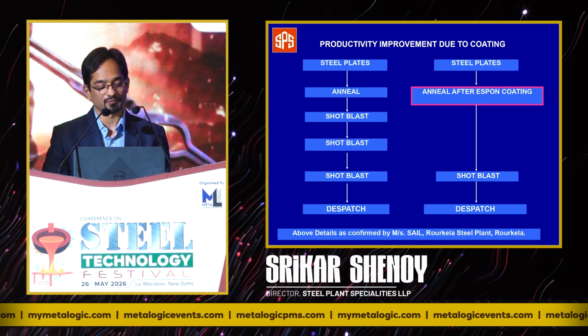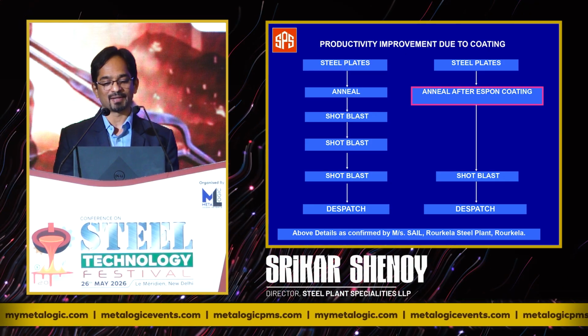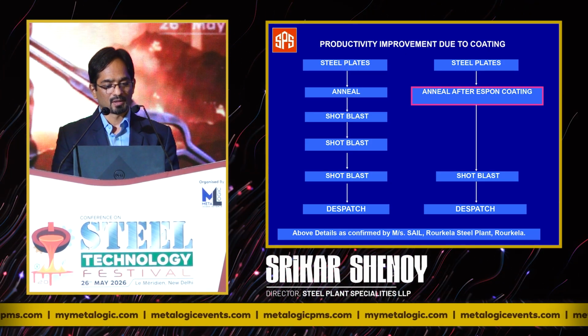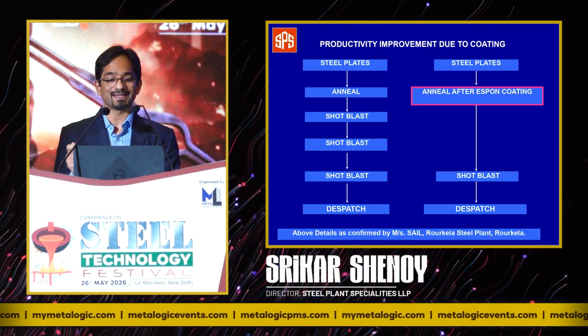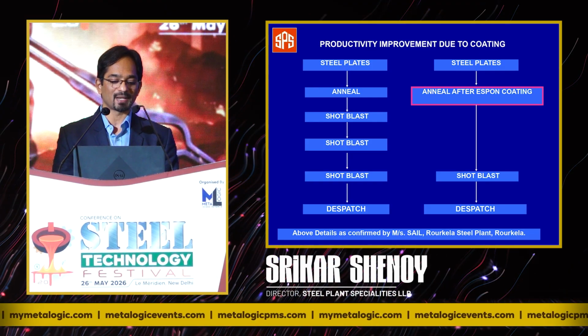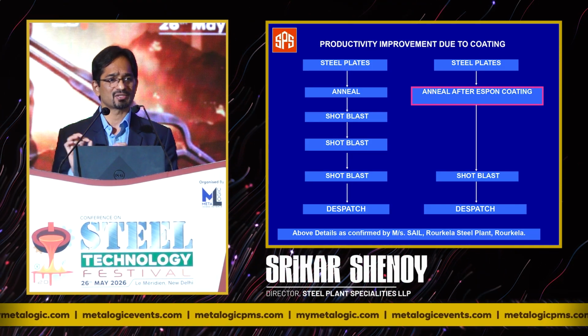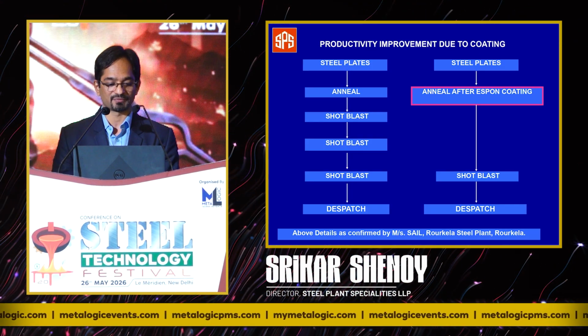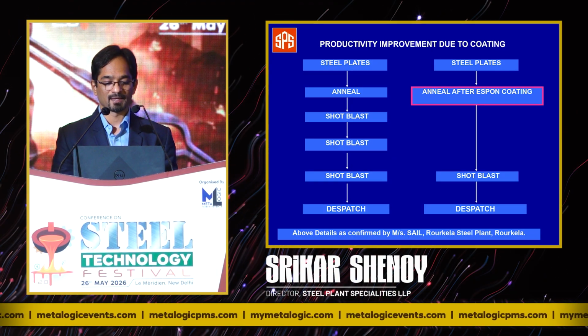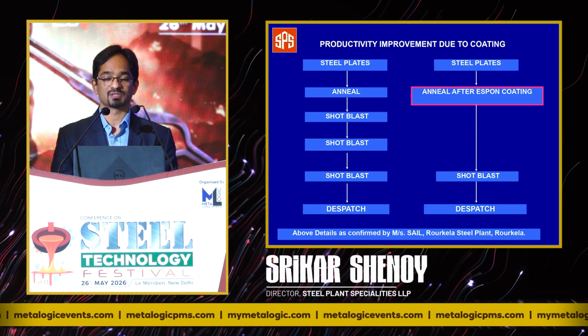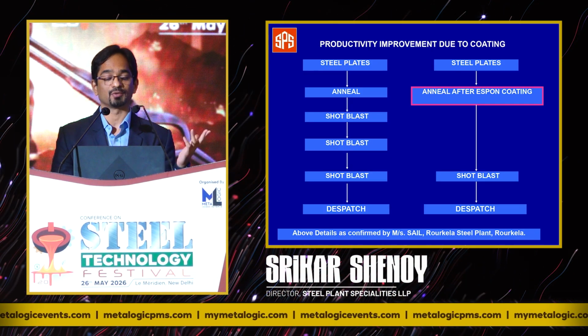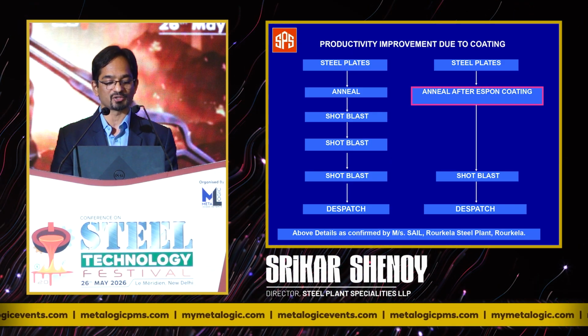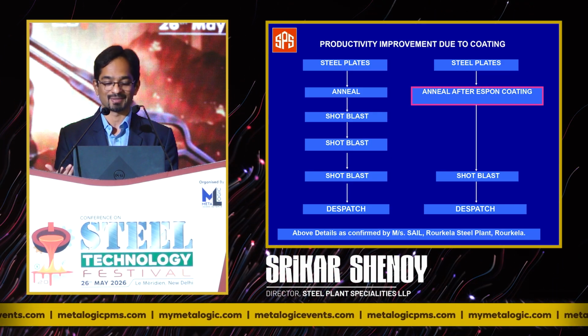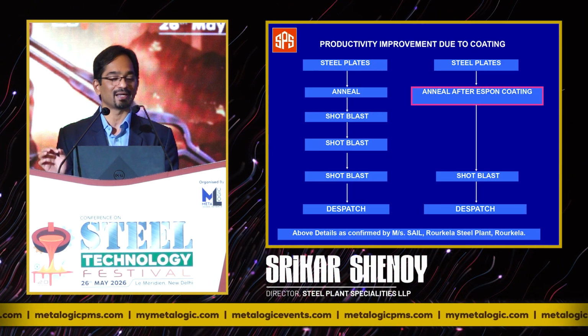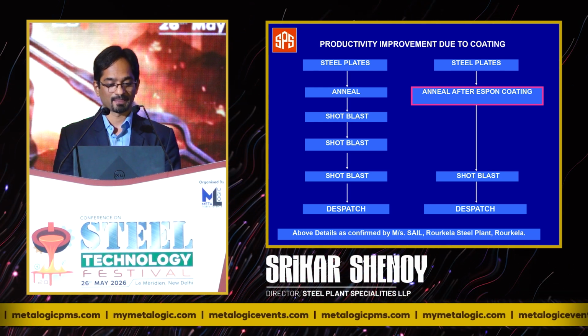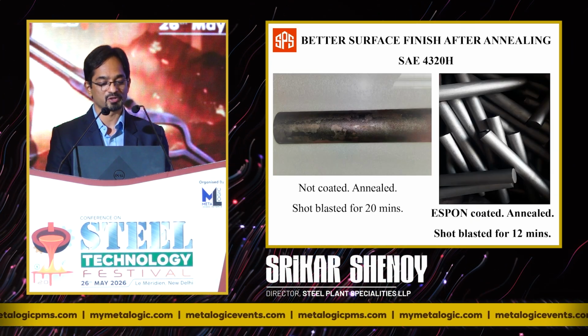This is a case study from Rourkela Steel Plant. Due to the presence of sticky scale, they used to carry out the shot blasting operation 3 times just to remove the scale and to give a good surface finish. By use of the coating, they were able to eliminate 2 shot blasting operations, and with 1 single shot blasting operation, they were able to carry out the dispatches. A 66% improvement in productivity. This is a more visual appeal.